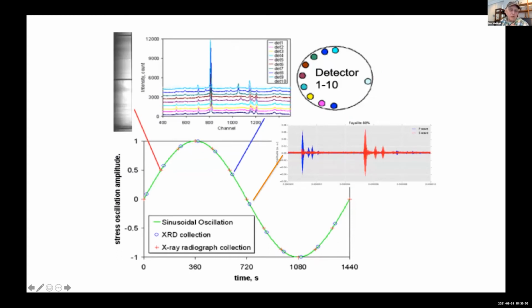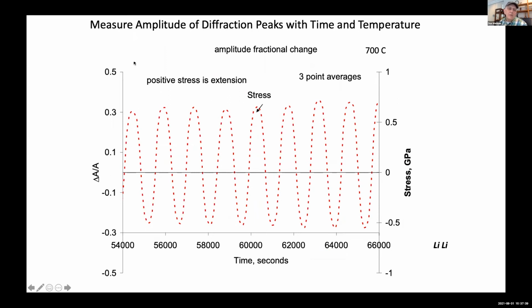The different measuring tools, we can define where the data is taken, embedded in the sinusoidal stress wave that we put into the sample. And this can be stress, it also can be pressure that we vary like this, but we can identify exactly the phase that we're going to collect the diffraction, collect the image, collect the ultrasonic signal, so that when we're analyzing all of this data at the end, we know all the phase relationships between the different parts of the signal.